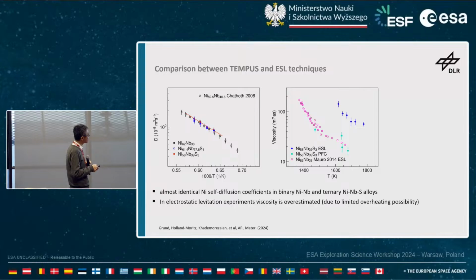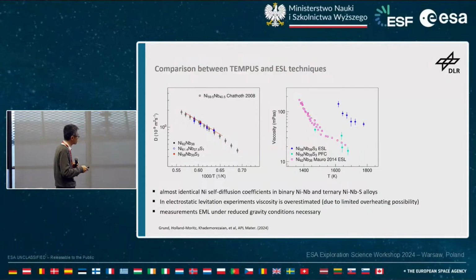And you see that the viscosity is overestimated in the ground experiment. This is actually not a real viscosity, but an artifact due to the limit of possibility in electrostatic levitation to overheat the sample. So the suspicion is we still have this layer of sulfur on the surface which affects the experiment. That's why the parabolic flight experiment is much closer to what we are expecting. This brings me to the point that we will really need this kind of experiment if we want to study properly the viscosity or the melt properties of these compositions, especially the sulfur alloys.